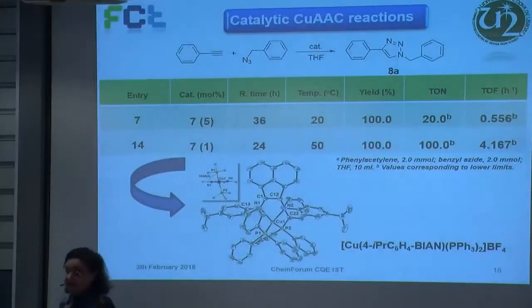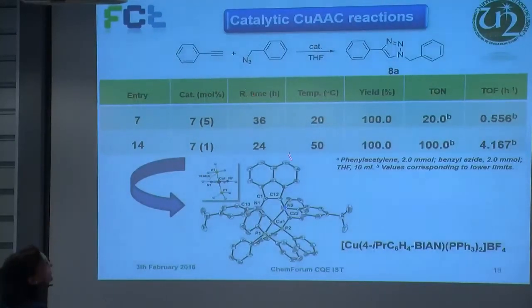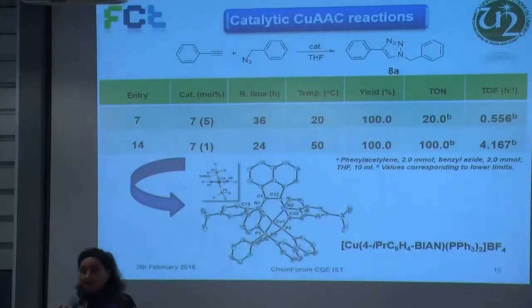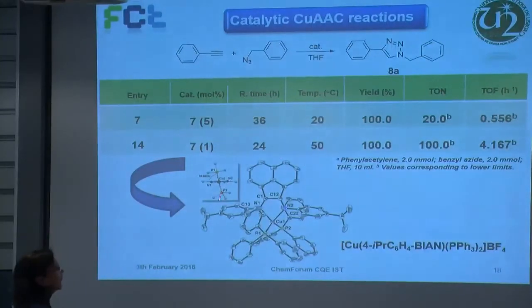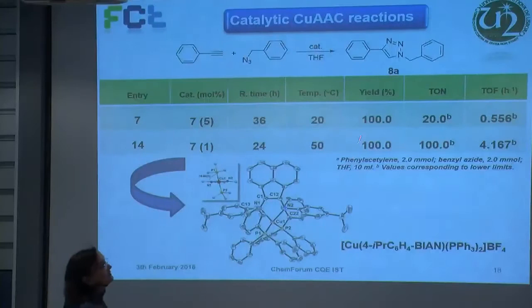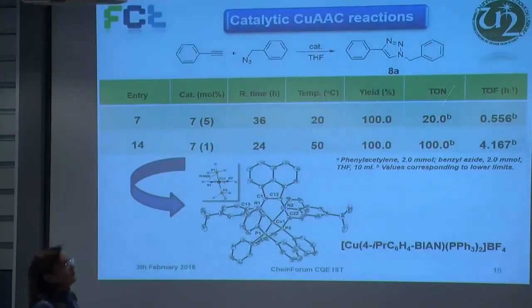Well, then the catalytic reactions were performed by treating phenylacetylene and benzyl azide in the presence of the catalyst and getting this triazole product. Among the compounds we tested, we found that one of the best catalysts was the one with the bis(triphenylphosphine). In this case, the reaction time was 36 or 24 hours, at temperatures of 20 or 50 degrees, and we had 100% yield. And here are the TON and TOF characteristics. So that was our best catalyst for this type of reaction.